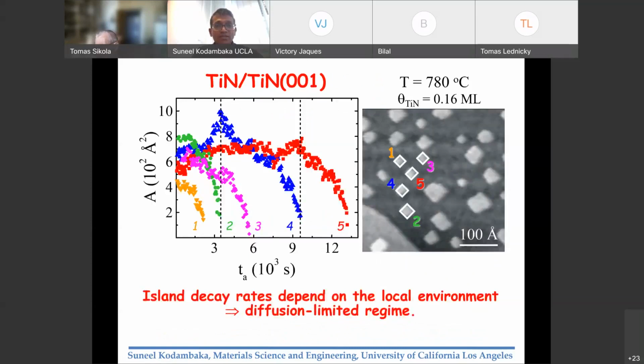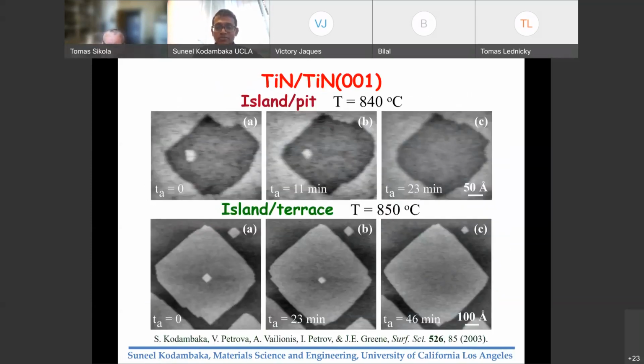Now, how do we quantify this behavior and what type of information can we extract from these types of studies? So for that, we prepared a carefully designed configuration. So this is a single atom island within a vacancy pit. So this is one step down, and this is a one atom high island. And as time progresses, it disappears because it loses atoms to the step edges of this vacancy island. And this is the opposite scenario where there is an atom island on top of a terrace. Okay, so a similar thing happens.